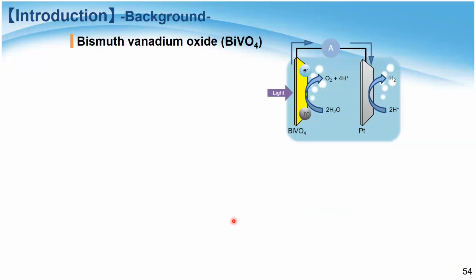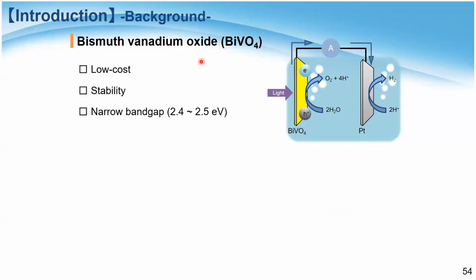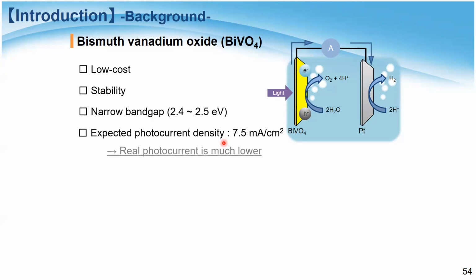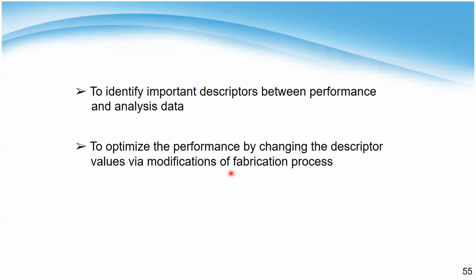So what we did here is that for bismuth vanadate, BiVO4, which is one of the famous photoanode materials, same as hematite, low cost and more stable than hematite, and visible light absorption, the band gap is about 2.4 electron volt, and the theoretical photocurrent density is about 7.5 milliampere, but still much lower than this. So the first thing we did is do the same things, the performance analysis, and then optimize the sample.